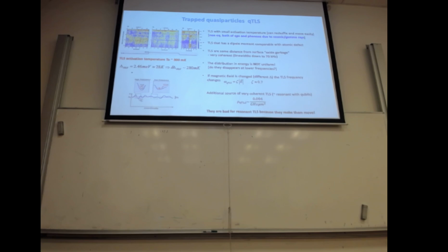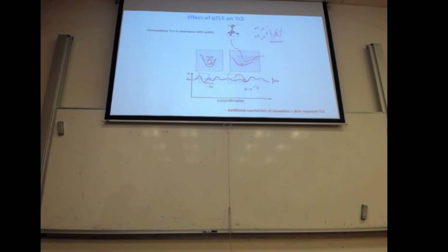There is another important point that he saw: when he sees these very weird 2LS and follows them, they are extremely coherent. So, looking at the coherence of the resonator, they are very coherent. And the other thing that tells you they are different from the others is that he could inject current in this resonator, and namely vary the delta of the resonator. And what he could clearly see, and that was a smoking gun, is that when he studied the coherent, special 2LS, it also varies, following the variation of the delta induced by the magnetic field. So this is really a strong indication that these two-level systems are special and they react to it.